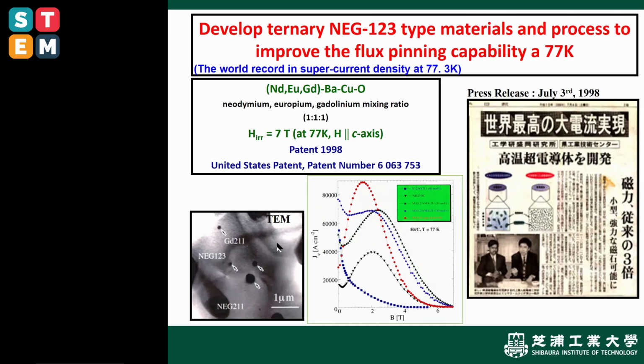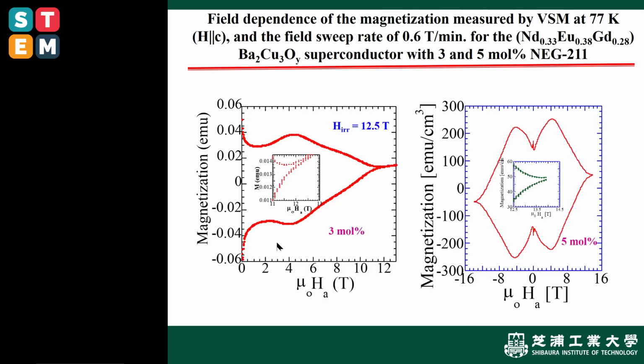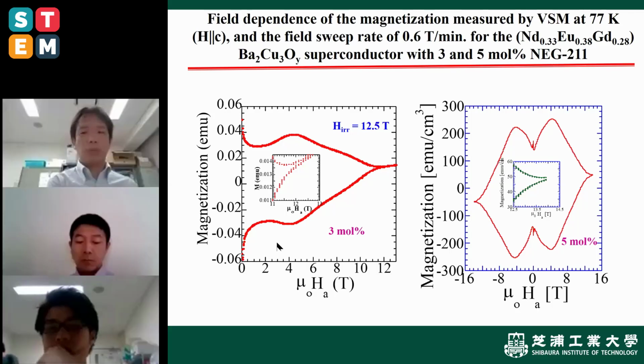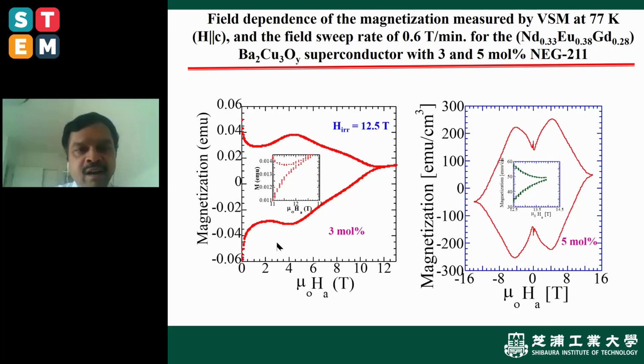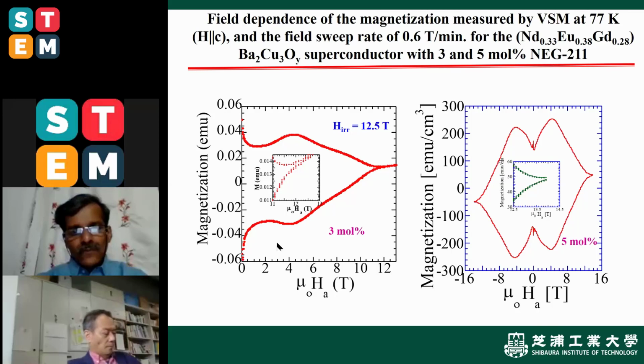This result led to several patents in the United States and Europe, as well as a press release in Japan. Further improvement of the field was observed, especially in the europium rich direction. When you make europium 0.38, gadolinium 0.28, this is the data I showed at 5 Tesla. This is also 77 Kelvin magnetization versus magnetic field. You can see 12.5 Tesla at 3 mole percent of europium rich NEG sample. But if you improve to 5 mole percent, it is more than 15 Tesla. This is one of the champion data to date.